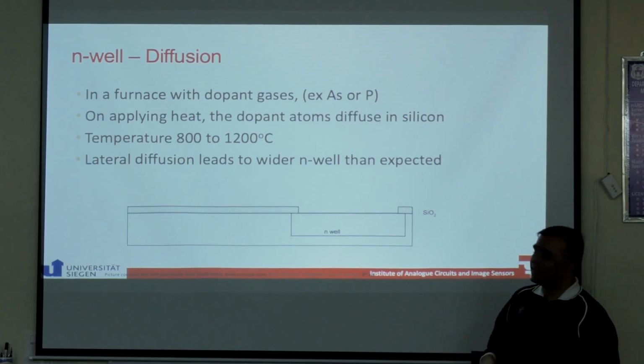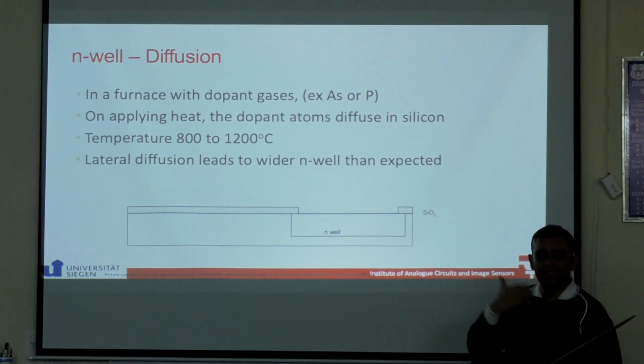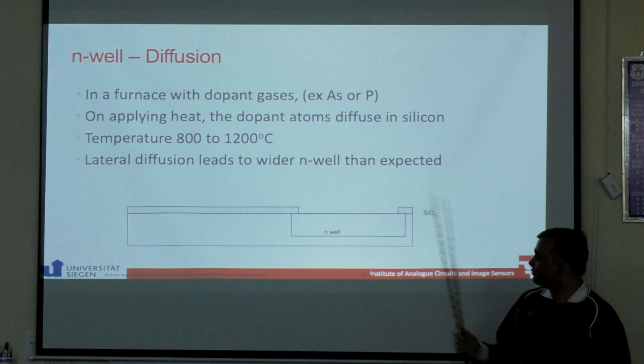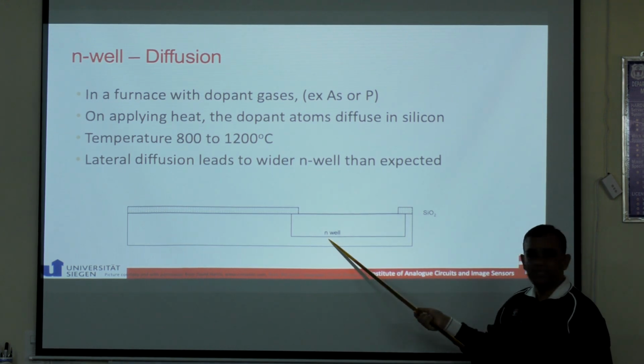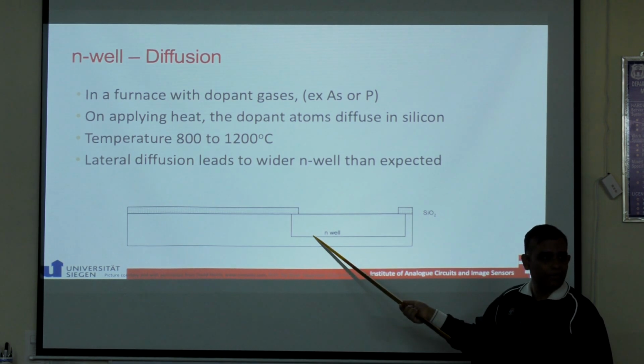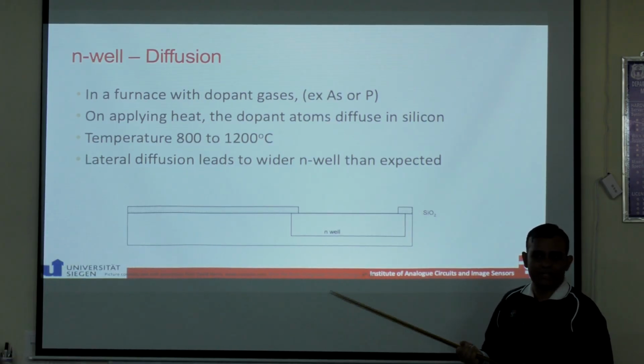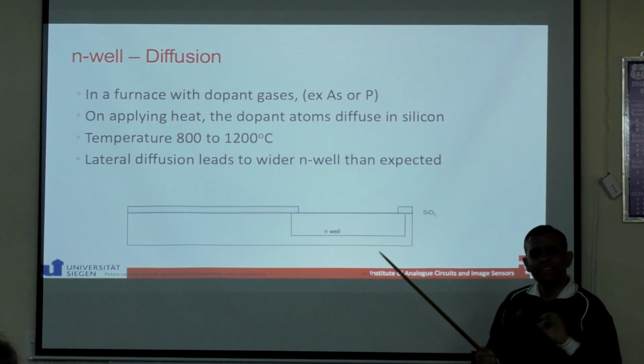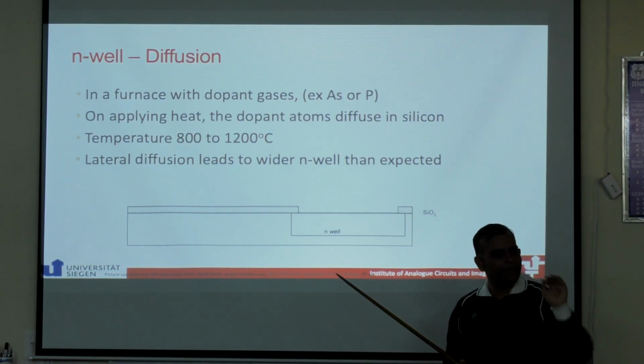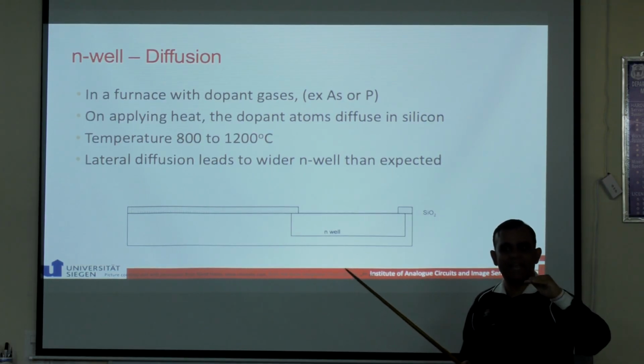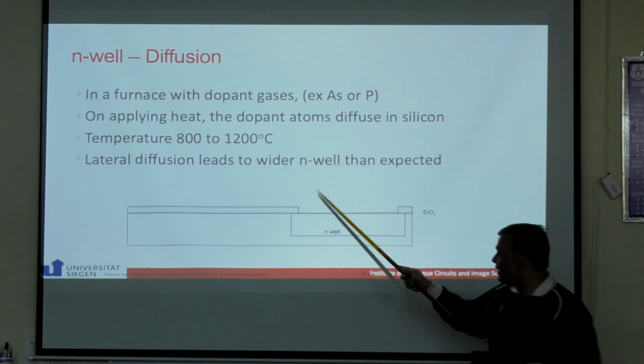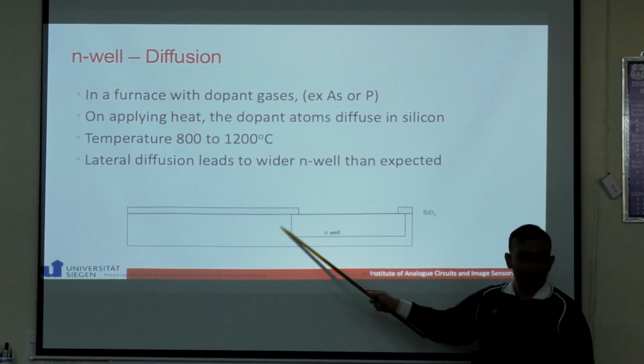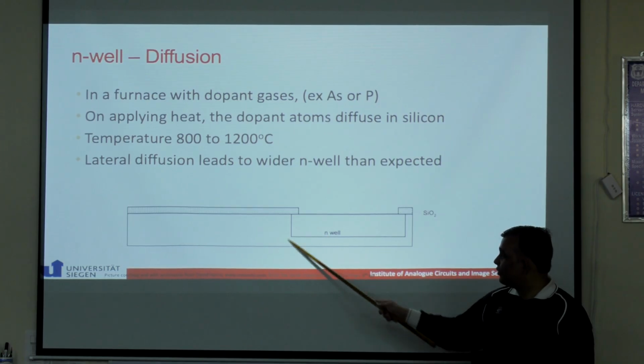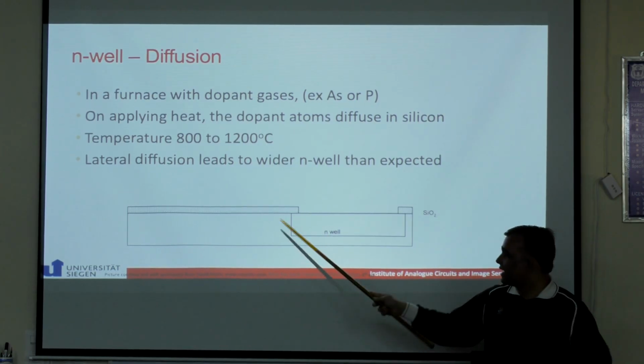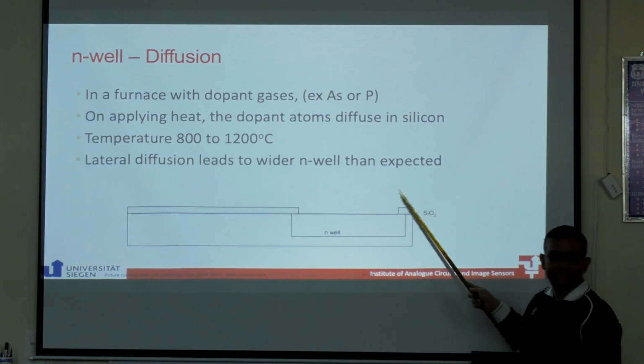And then we pass some dopant gas, arsenic or phosphorus, at generally high temperature, 800 to 1200 degrees Celsius. So that dopant enters the silicon substrate and it goes from P-type to an N-well formation here. Okay. Now this is the process which is a bit tricky, because based on the temperature and pressure of the gas, you could have lateral diffusion, things could go this way, and you can see there's already some. Even though I have drawn it as a rectangle, it never forms a rectangle. It's always a structure like this.